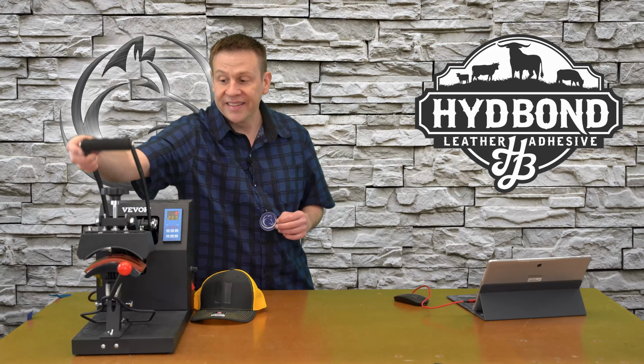I spoke with Josh, one of the co-owners of Hydbond, and to properly activate the Hydbond adhesive, he suggested getting the Hydbond adhesive up to at least 220 degrees Fahrenheit for a minimum of 10 seconds. So in a minute, we're going to take a look at the settings that I have on this hat press. But first, I'll turn the power on and let this get up to temperature.